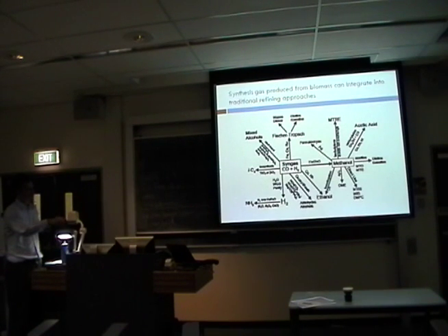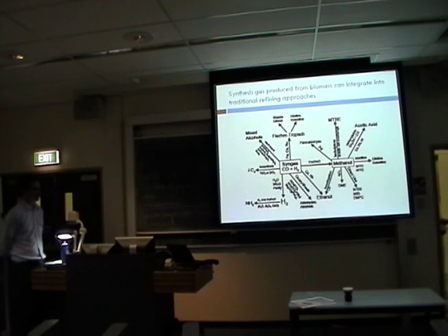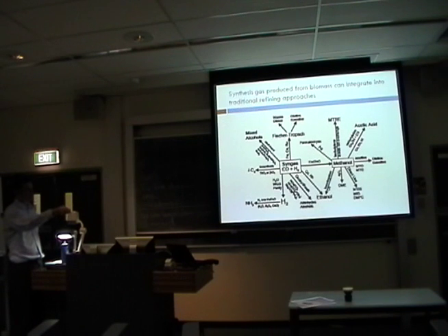You can also use a metal catalyst, copper and zinc oxide, to make methanol, which is another potentially useful product that people have proposed using in direct methanol fuel cells, for example. And also as a useful intermediate that you can react over zeolite catalysts to make gasoline, for example. And it's called the MTG process, methanol to gasoline. And there are processes to get to ethanol, which there's sort of a mandate to produce a lot of as a biofuel.